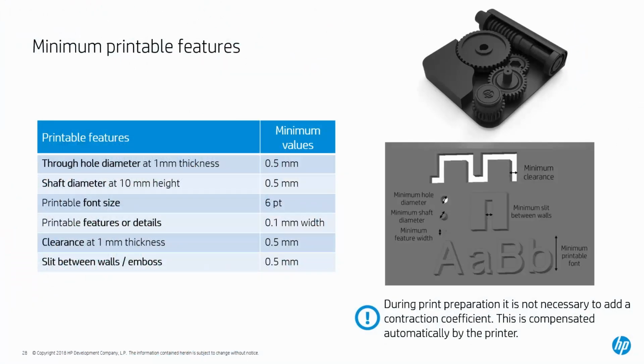When we look at the basics of designing parts for MJF, we have some minimum features that we suggest you use. You can go much larger than this, but this is the minimum. If we have a small hole going through a part, you need to remember 1/2 millimeter. Most small features on a part are going to be a minimum of around 1/2 millimeter, unless it's a feature such as a texture, where you can go a little bit smaller. But 1/2 millimeter is about the smallest distance you're going to use, either for a through hole, a cutout, an embossing, or a font size.